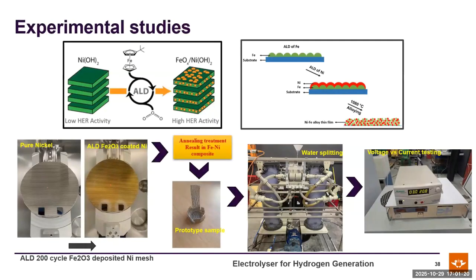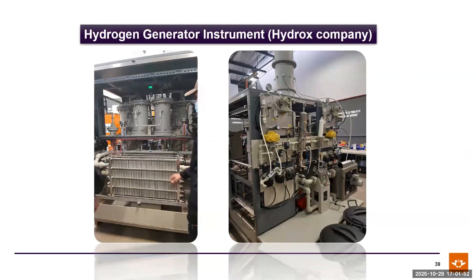So we did an experimental study, and we deposited using the ALD process, annealed it, and then did the water splitting, the alkaline hydrogen generation. You can see that one in the water splitting. That one currently resides at Hydrox, and it has much higher power, 1.1 kilowatt, and we can record the result. It actually shows a quite similar result. And this is another hydrogen generator instrument, the one that is commercially available, about 20 kilowatt. This is the one we're trying to move to our facilities, because UJ wants to have this facility for next generation development.